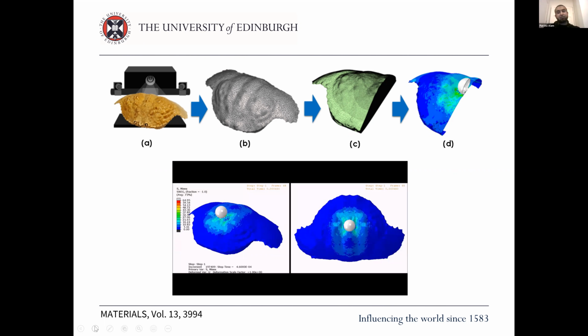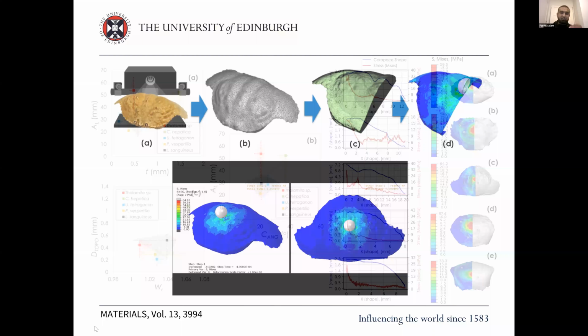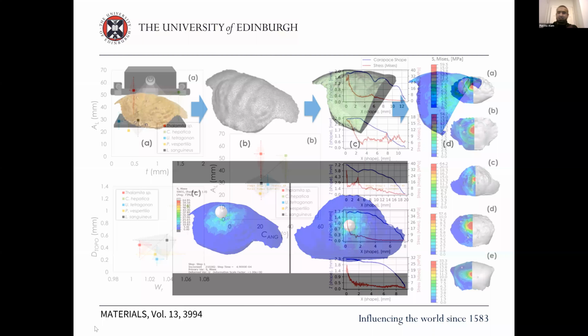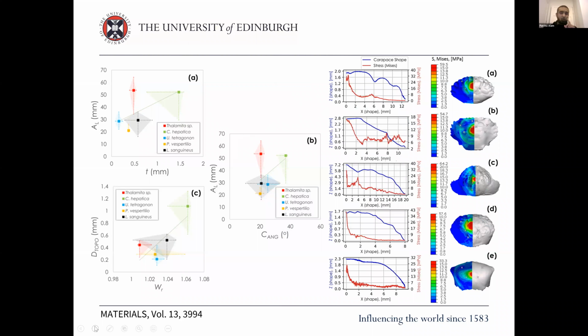One of the things that we did notice is that while there were mild correlations between different morphological features of the crab shells, such as the arc length, the thickness, the carapace angle, the topographical irregularity, and the Wenzel roughness, there were very clear correlations when it came to stress peaks, where there were deep valleys in the crab shell. So basically, the deeper the valleys were, the higher the stress peak. And since crab carapaces are brittle materials, it follows that if you have a stress peak in a valley, or where there is a geometrical change on the carapace surface, you'll probably end up having some issues.